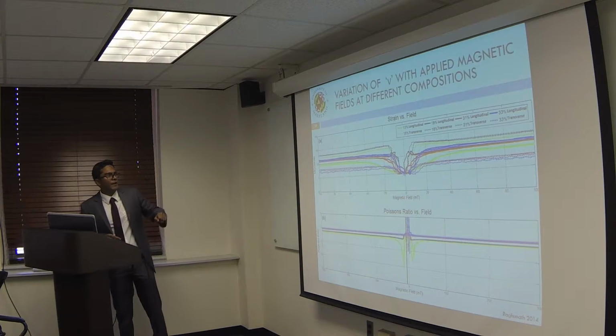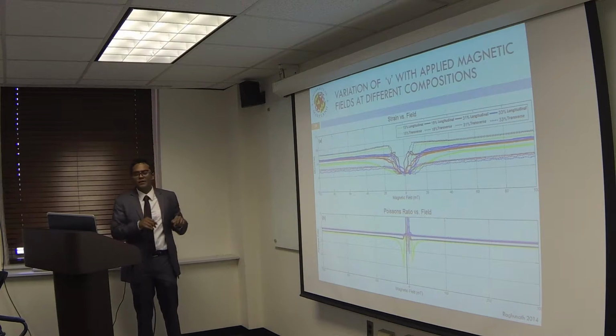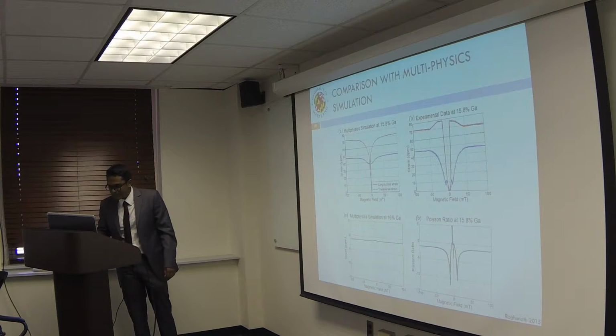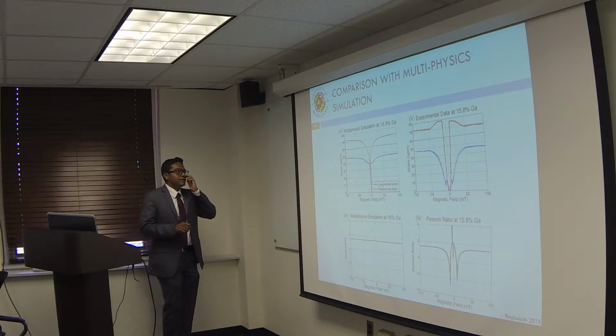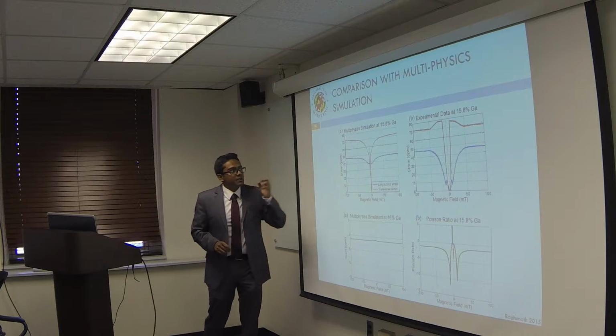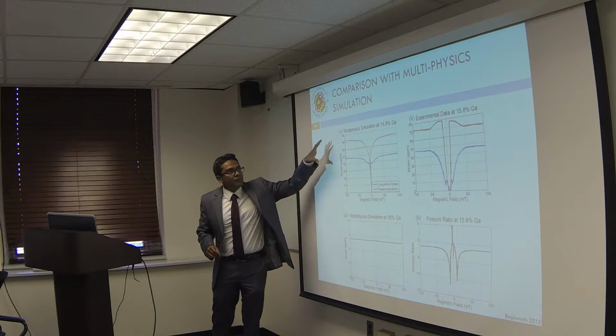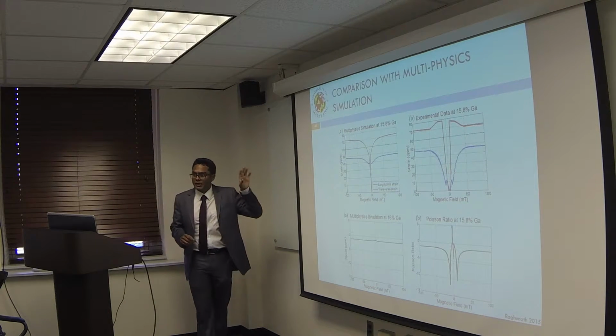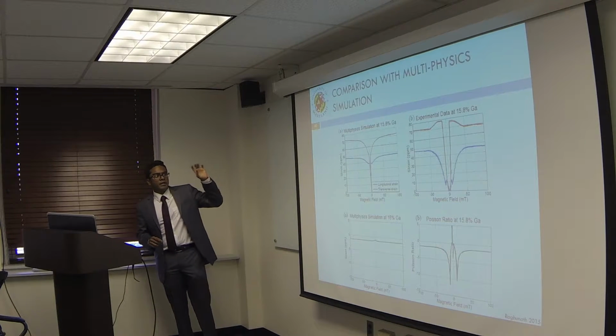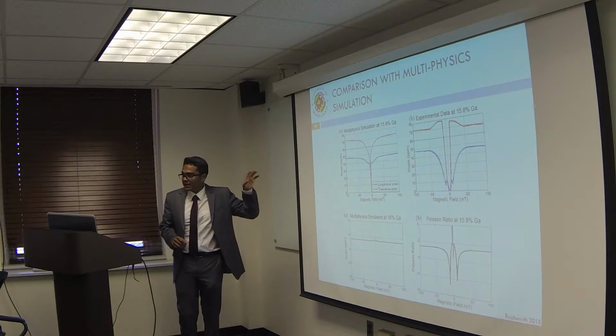This chart shows you raw data from all the samples. It's too cluttered, so I'm not going to go into the details of this. So here's the comparison with the multiphysics simulation. The simulation was able to predict the values at magnetic saturation pretty darn well. The error percentage was less than 10% at magnetic saturation.